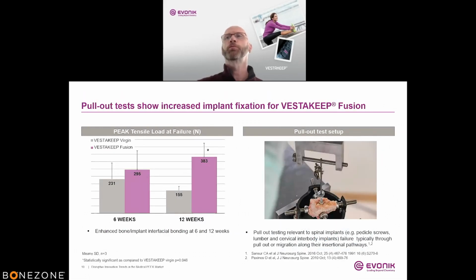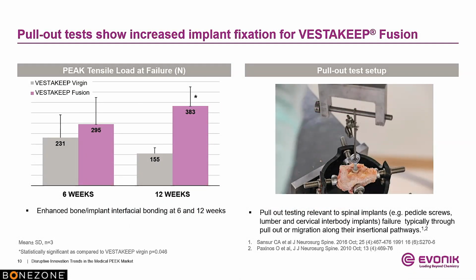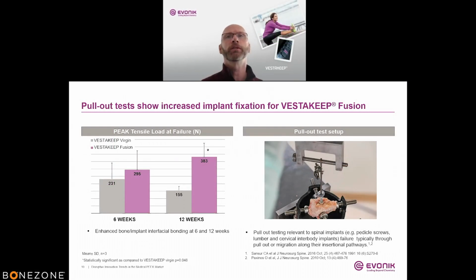Pull-out testing, or biomechanical testing, was performed to assess implant fixation, both at the 6 and 12 week time points. When we see the 6 week time point, there's less of a difference than at 12 weeks, and I think it's probably more influenced by the inflammatory response to a foreign body in the animal model. What we see at the 12 week time point is really the apposition of the implant by bone, the densification of bone, and the resorption of bone. So what we're seeing at the 12 week time point is going to be very representative. And we see a 2x difference between the unfilled PEEK versus VestaKeep Fusion.